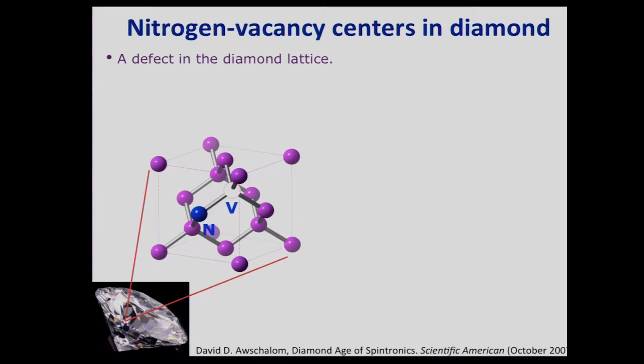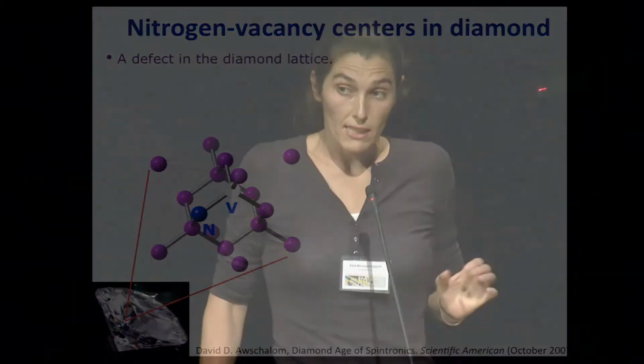Okay, so what is the NV center, the nitrogen vacancy center? Diamond is a carbon lattice. An NV center is a defect in the carbon lattice, where one carbon is removed and replaced by nitrogen, and right next door a carbon atom is removed and not replaced by anything; it's a vacancy. These occur naturally. In fact, defects in diamond and other stones are what give them their colors. An NV center would make diamond pinkish, reddish. But one can also cause them to occur by implanting nitrogen and subsequently annealing the diamond. By annealing, the vacancies become mobile, and they like to land near the nitrogen. They form a nice stable atomic-like complex there.